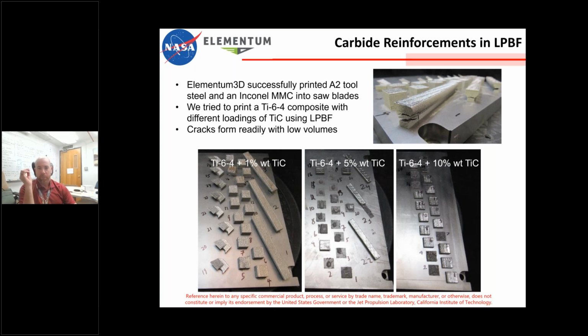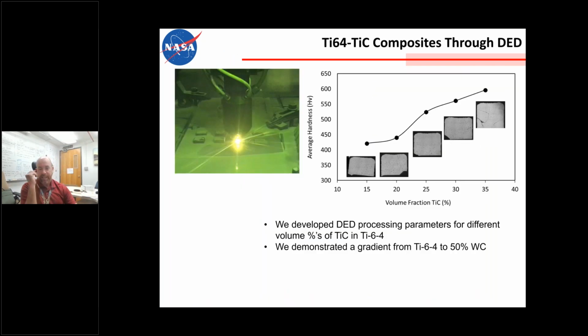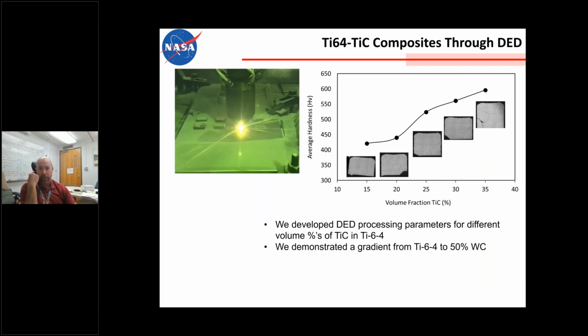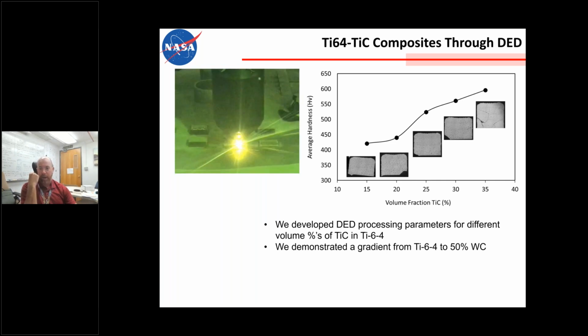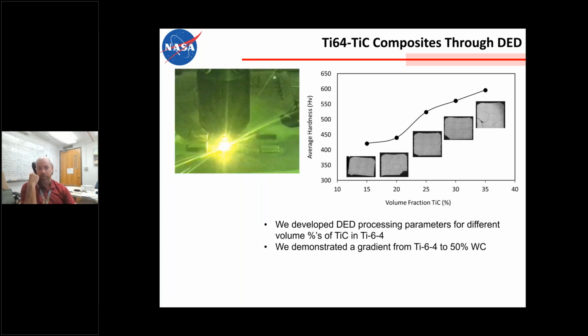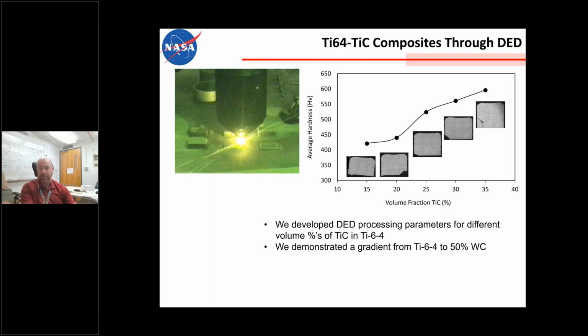So this is part of the process of doing alloy development—figuring out what works and what doesn't work based on the available parameters. So we switched to DED to be able to try to do these Ti-carbide loaded Ti parts. We're able to get up to about 30% loading of Ti-carbide before we start getting significant cracks in the Ti-6-4.